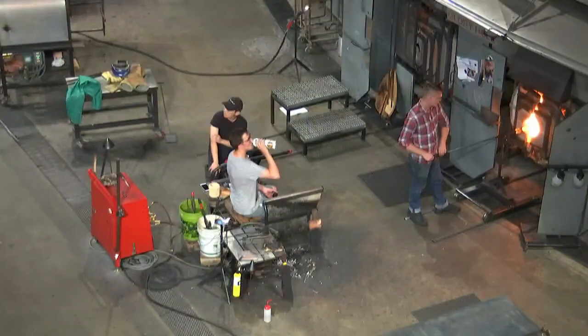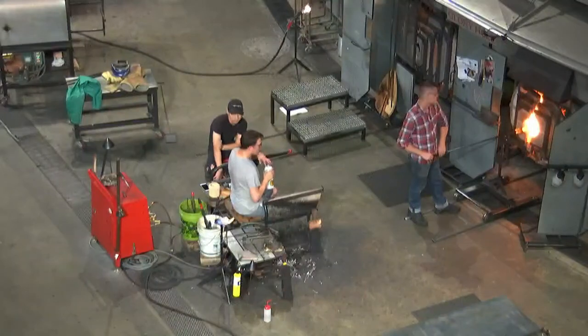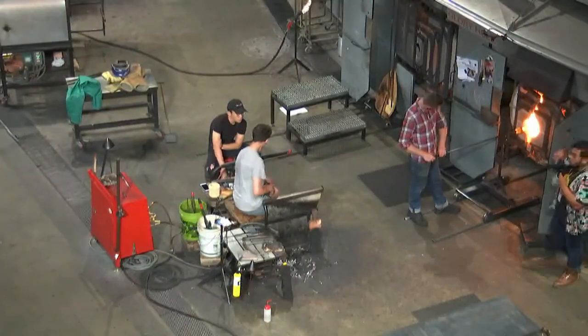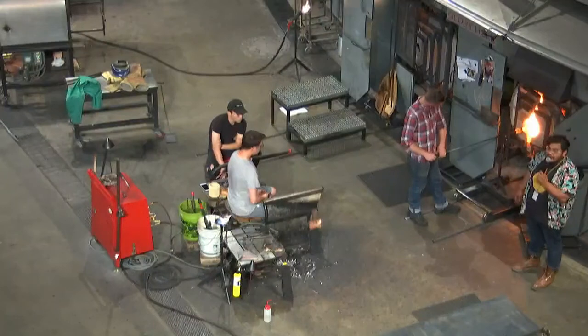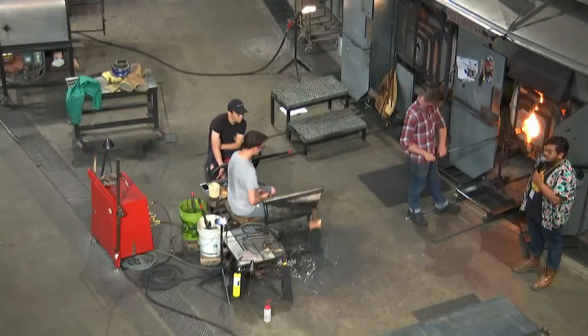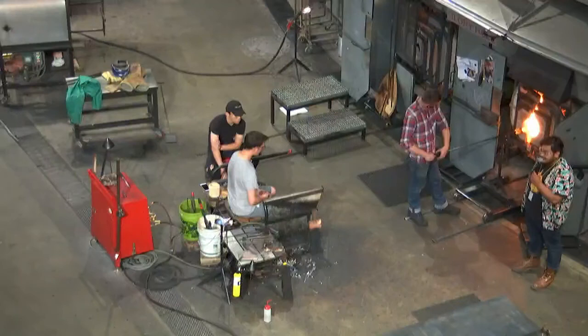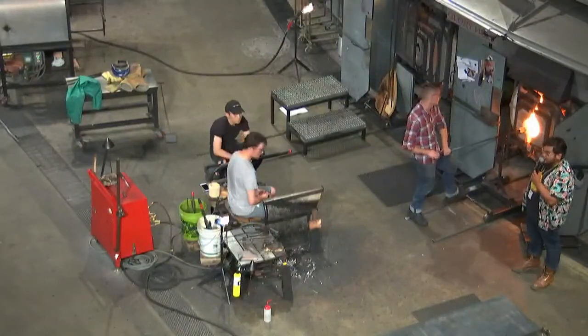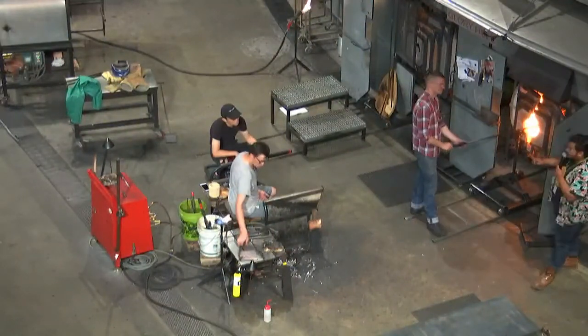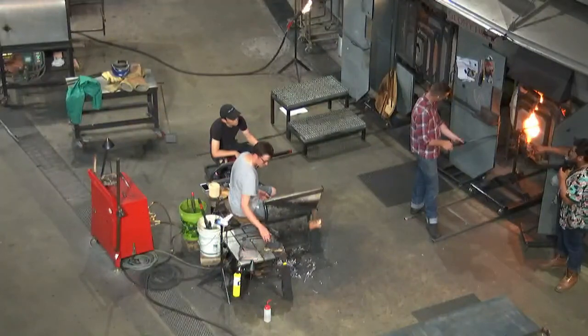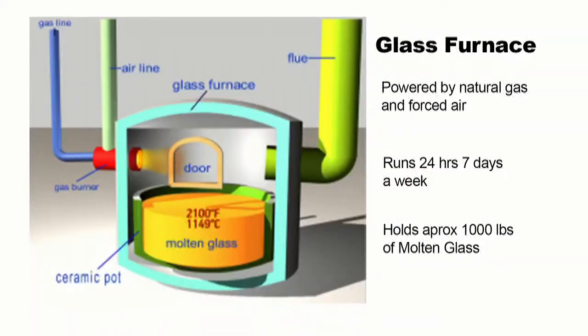Once the glass exits this furnace, it immediately begins to cool down. So we then enter what we call a glory hole, which is the reheating chamber, a round barrel on its side, lined with fire brick made to insulate and keep the heat inside. It's slightly hotter than the furnace at 2300 degrees, but you'll notice the glass makers will manipulate the glass and then re-enter the chamber for continuing melting and also to continue manipulating the massive glass. On our top screen, we are going to go through a couple slides of the equipment that we have here just to simplify and understand what's going on here.